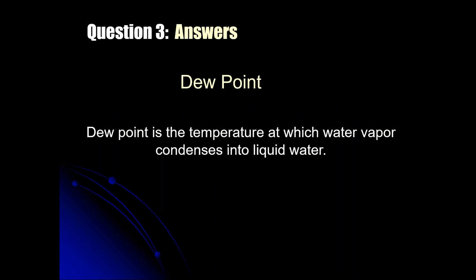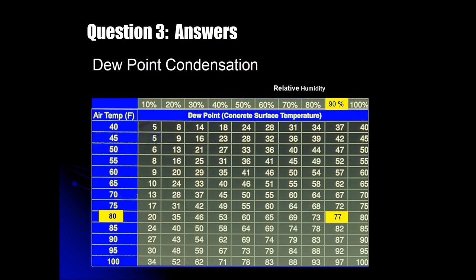Well, by definition, dew point is the temperature at which water vapor condenses into liquid. Here you see a dew point chart. And the point I want to illustrate is how close a dew point temperature can actually be to ambient conditions. For instance, here we have an 80 degree Fahrenheit day with ambient relative humidity at 90%. The dew point is only 3 degrees lower than the ambient, which means, and you can use a classic example, taking a shower, opening the shower stall door, and that warm, humid air condenses on your mirror, which is colder. That's dew point. But the point here is it can at times be very close.